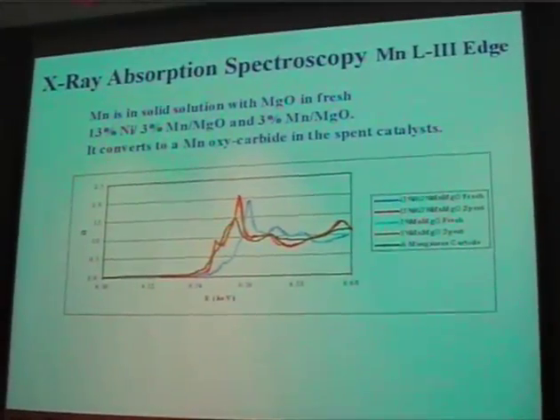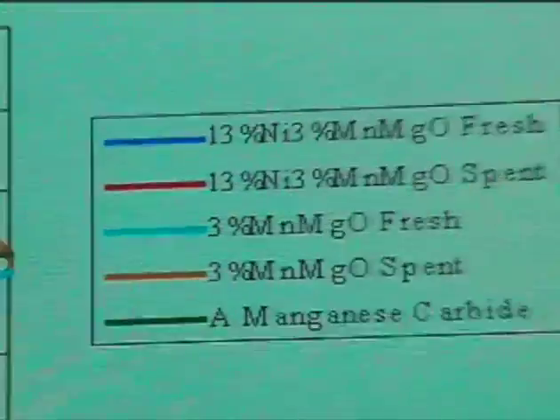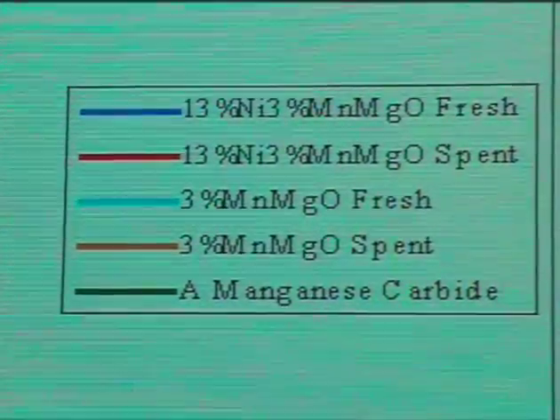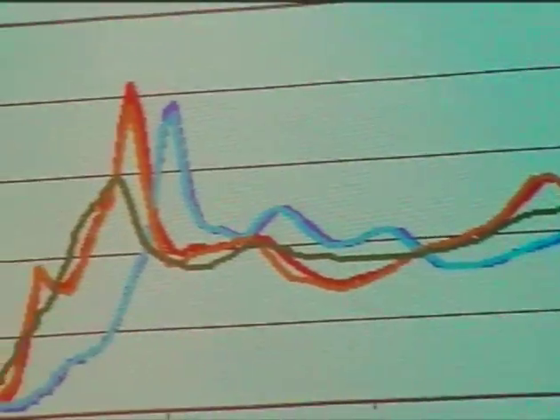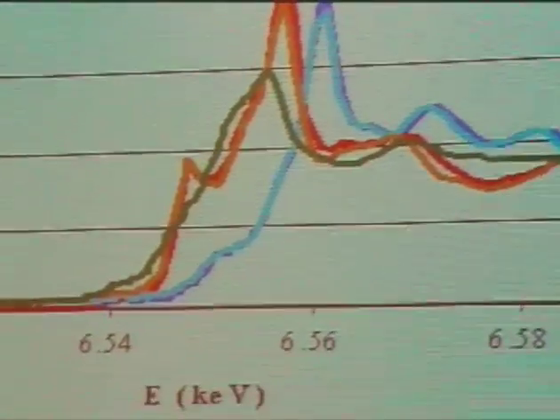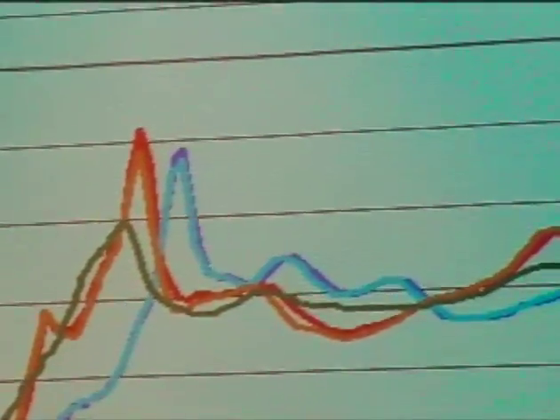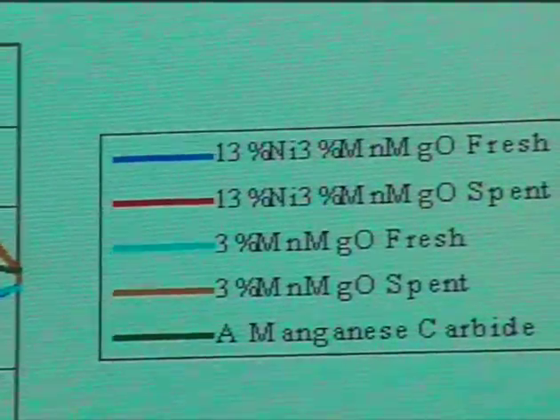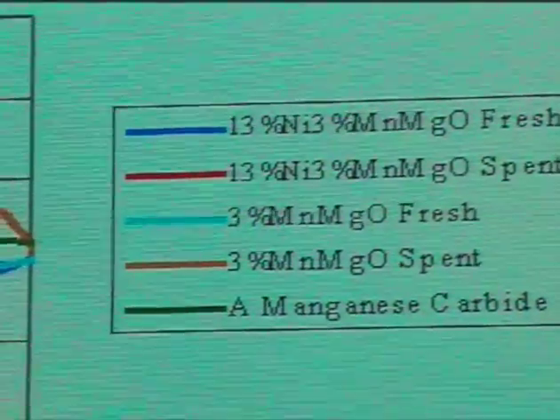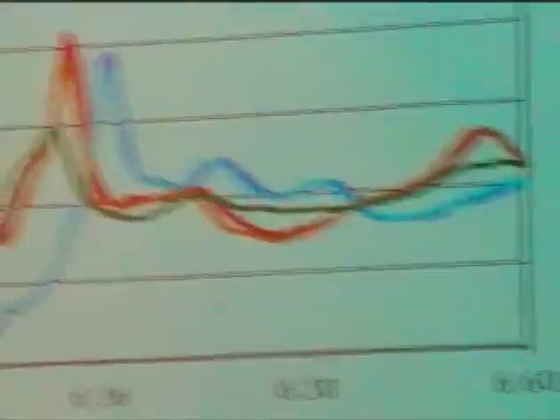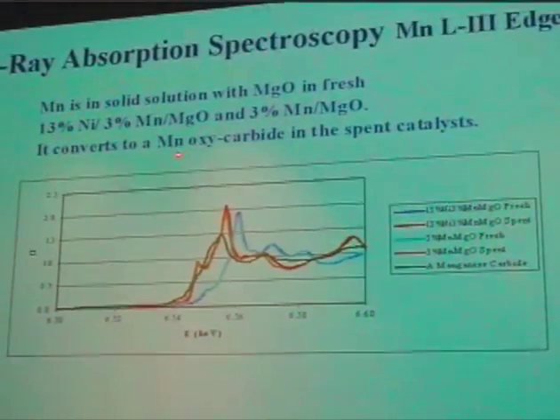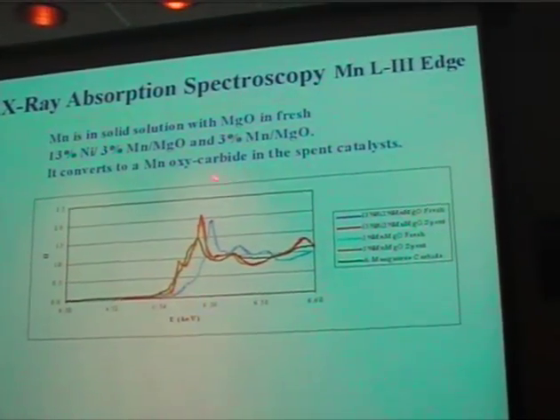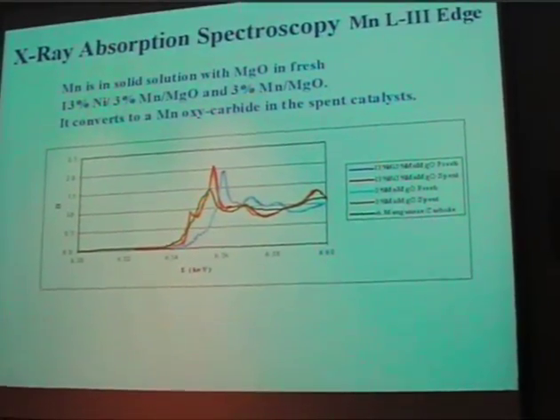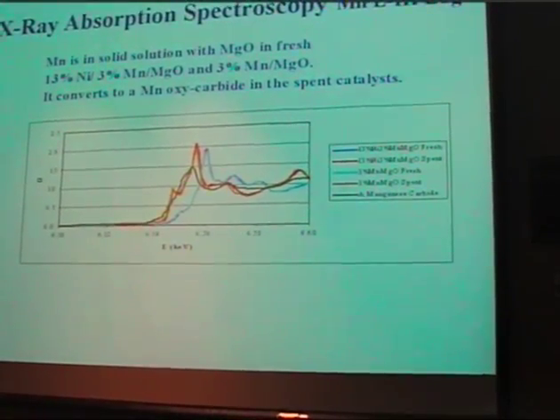And we also looked at the manganese, because we were interested in what oxidation state the manganese was in. And the data would support that the fresh catalyst would be in a manganese +3 oxidation state, whereas the spent was a +2. So the manganese is undergoing reduction. And as far as looking at what happens after the catalyst is used under 8 to 10 hours, the data would support the conclusion that perhaps a manganese oxycarbide is being formed. Although this isn't conclusive, it would be in support of that information.